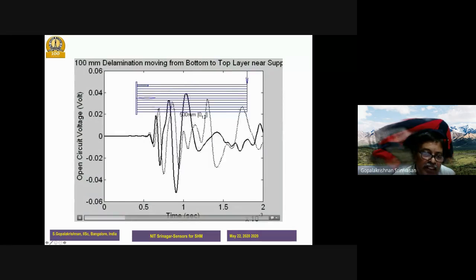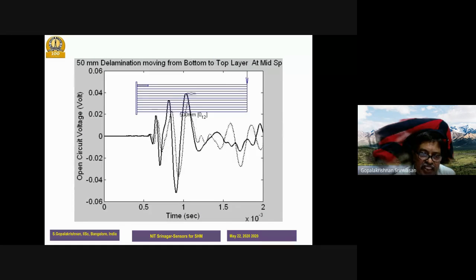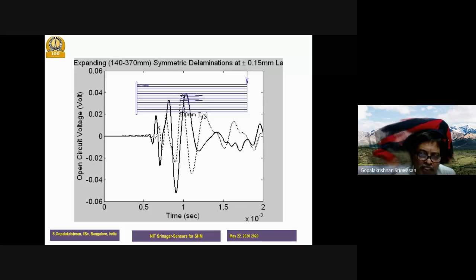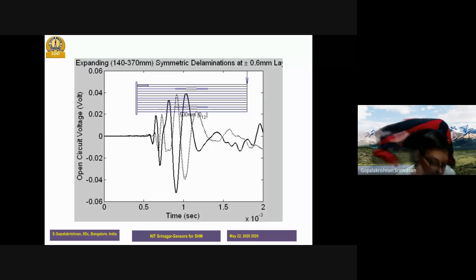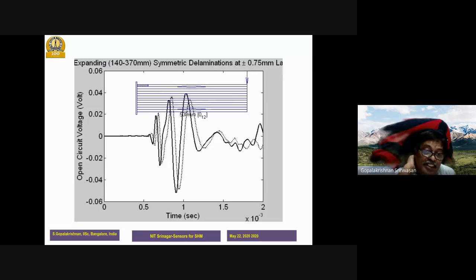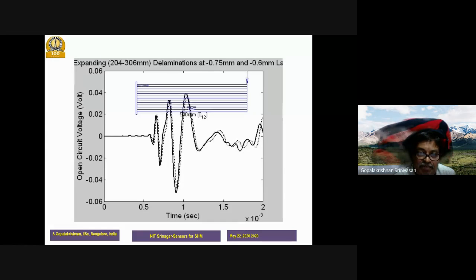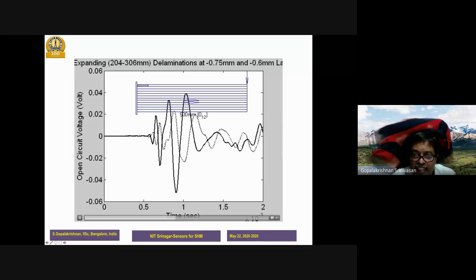You can see when the laminate position is changing, the standard one, the black one, is the healthy one. But as the laminate size grows, you could see how the open circuit voltage changes. Based on it, we can find out whether the damage is there and where the damage is. You could see for different levels, the size of the damage. For small size, you have 1 delamination, 2 delamination, and all of these were captured experimentally.